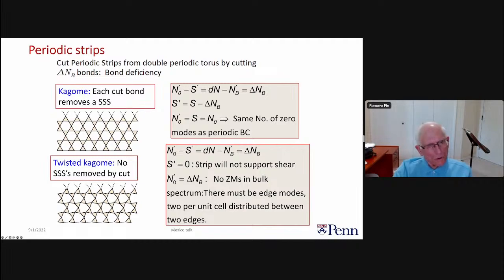We still have removed 2 bonds per unit cell, but we've lost the states of self-stress. So now S prime is equal to 0. And when you go through the algebra here, N0 prime is just equal to delta NB, the number of bonds that have been cut per unit cell on the surface. So that means that we necessarily now have 2 extra zero modes on the surface per unit cell coming from that.